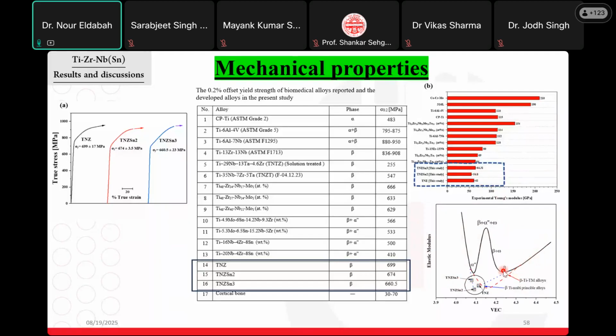But you can find there is an inflection, and from literature, for titanium based alloys, a BCC beta phase can obtain a low elastic modulus. If we can obtain this minimum point at lower valence electron concentration for binary alloys, we will obtain a lower elastic modulus. In our case, we have shifted this lower peak to a lower valence electron concentration, and this was the target of this study, to reduce the elastic modulus. We faced this inflection, and it increased back again. This may most probably be due to precipitation of a nano precipitation phase, as in such types of alloys.